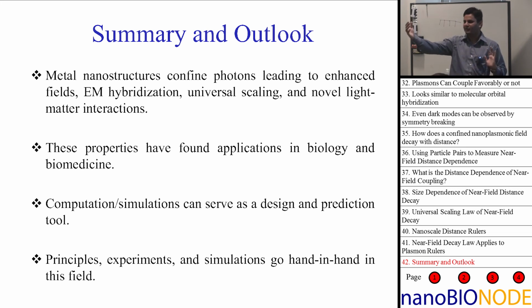You can't make the structure much longer than the wavelength of light, but that's not the case with 5 particles. When you have a string of 5 particles, nearest neighbor interactions are the strongest. The near field falls exponentially away from the particle. And so the 5th particle really doesn't influence the 1st particle, but it does influence the 4th particle and so on. So the result you will see will depend mostly on nearest neighbor interactions and less on these long range things.